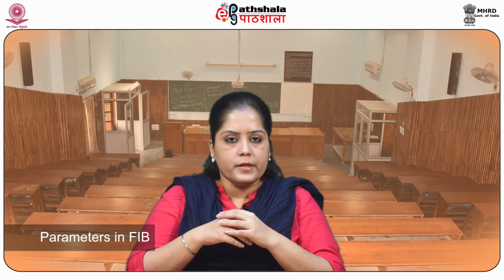So students, let us now discuss some of the parameters in FIB. The ion beam source is a liquid metal ion source, especially a gallium ion source. The acceleration voltage of ions is typically of the order of 1 to 50 kilo electron volt. So the resolution of the feature size is better than 10 nanometers.